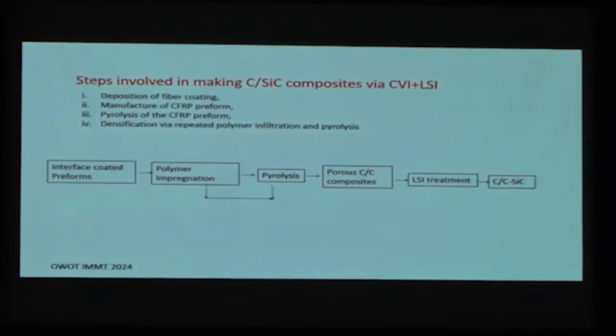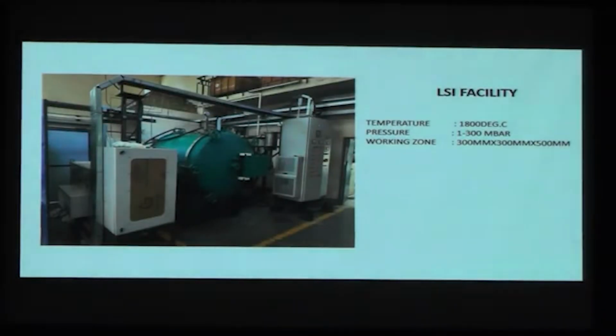So here first I took the preform, go for the polymer impregnation, pyrolysis, again go for impregnation, pyrolysis, like that I do it for 5-6 times. Then I take it for LSI treatment, and finally my composite is ready. So this is a facility available at NAL, recently established under mission mode program, where this can go up to 1800 degrees centigrade and 1 to 300 millibar is the capability. Depending on that, you can play with that. So this facility is used for making this brake disc.